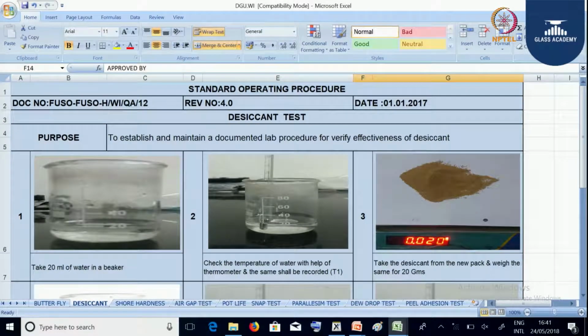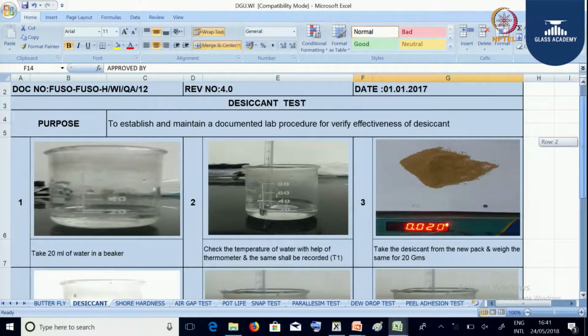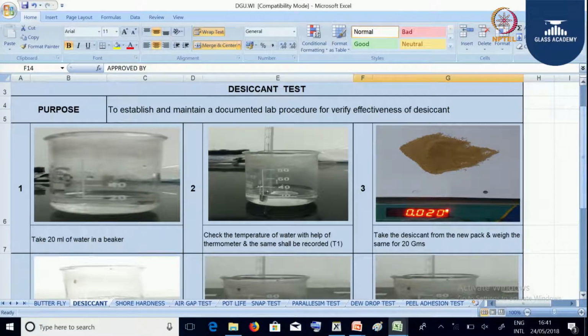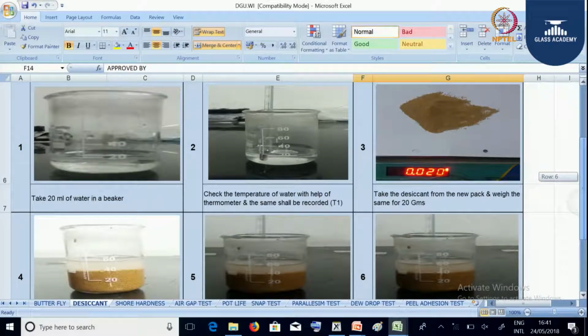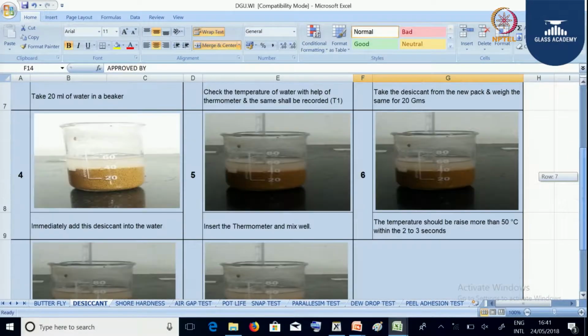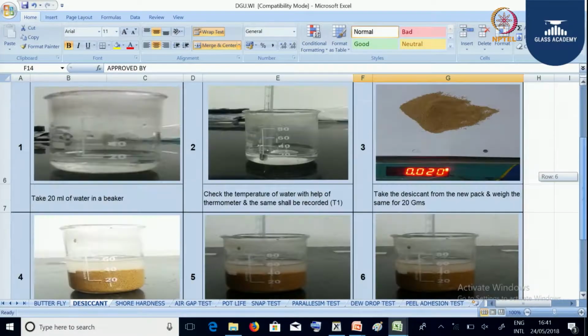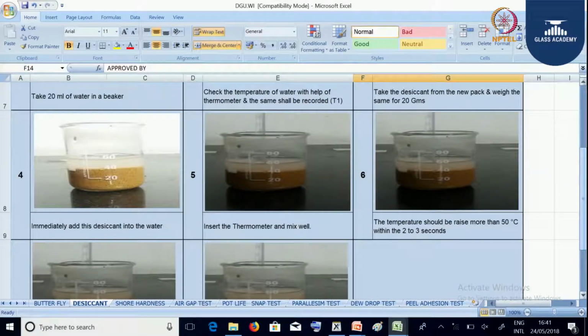Next test is the desiccant test, which we use inside the spacer to absorb moisture. First we take 20 ml of water in a beaker, then measure the temperature of the water. Then we take 20 grams of desiccant and pour it inside the water, and check the temperature after the desiccant is kept inside.